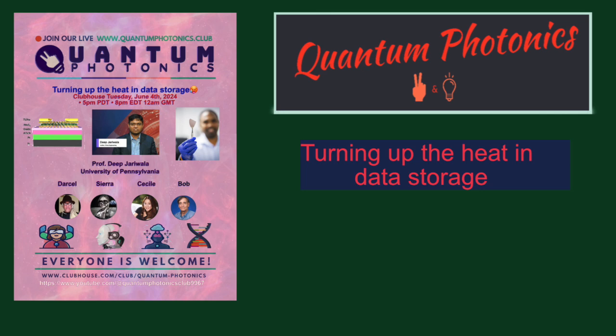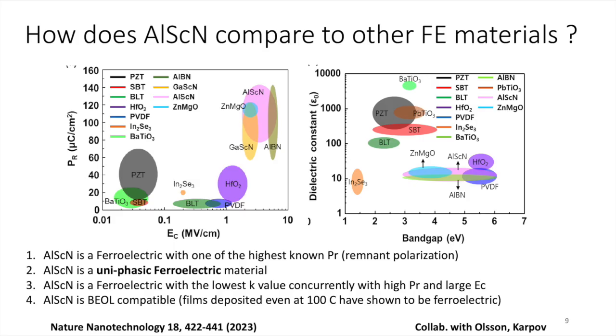Yeah, it's a good question. Let's go back to slide 9. On slide 9, I was showing you this is a full class of materials. This is no longer just aluminum scandium nitride; it's not just one material. There is a whole class of III-nitride or wurtzite-type ferroelectric materials. There is zinc magnesium oxide as well. There is gallium scandium nitride. There's aluminum boron nitride. There is aluminum yttrium nitride. There are like 5, 7 of these different classes of materials that have been found. We don't know which one is going to be the best material among these, to be very frank and honest with you.